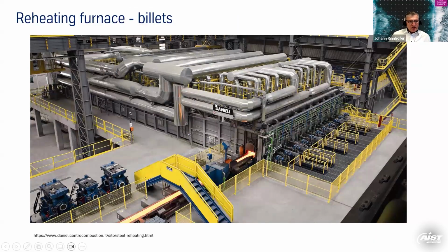How do these furnaces look? You come in cold on the left side, you go through the furnace, you end up hot here, and exit the furnace also through a little door on the side in order to prevent air ingress. You see the small burners here in the soaking zone because, as I said, not a lot of heat transfer, small burners. We have a lot of heat transfer in the heating zone, large burners. And you see here the insulated air system. This combustion air is usually heated to 400 to 600 degrees Celsius in order to save some natural gas.